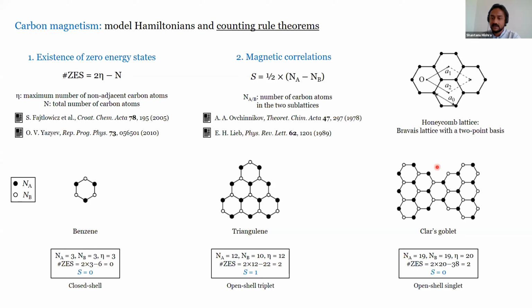And that's exemplified by this structure called Clar's goblet, where the choice of the maximum number of non-adjacent carbon atoms is a bit non-trivial. So if you consider this half of the molecule and you take only atoms belonging to the sublattice A, there are 10 of them, and you take this half and you take only atoms belonging to the sublattice B, and there are again 10 of them, then you end up with a total of 20 non-adjacent carbon atoms, and there are 38 carbon atoms in total, so you still get zero energy states. However, since you have an equal number of A and B sublattice carbon atoms, the spin is 0 now, so it's an open shell singlet. So you see how by tailoring the shapes, one can really change the magnetic correlations in nanographene.